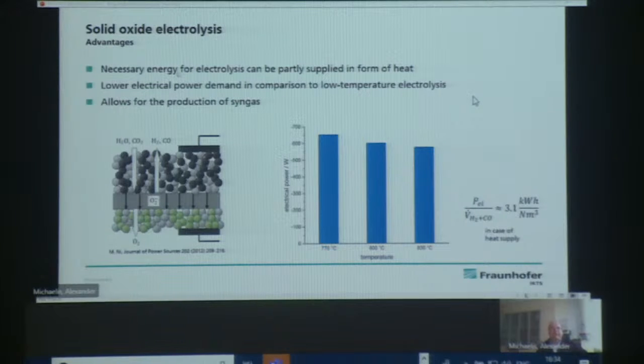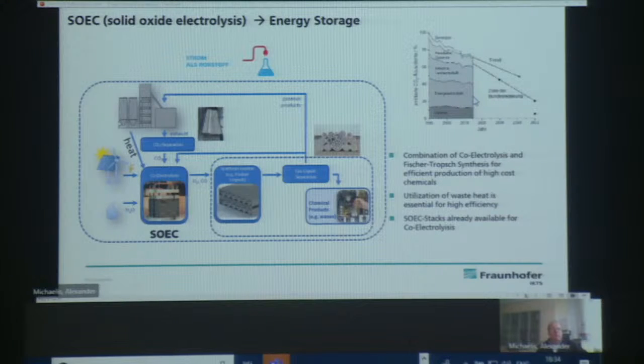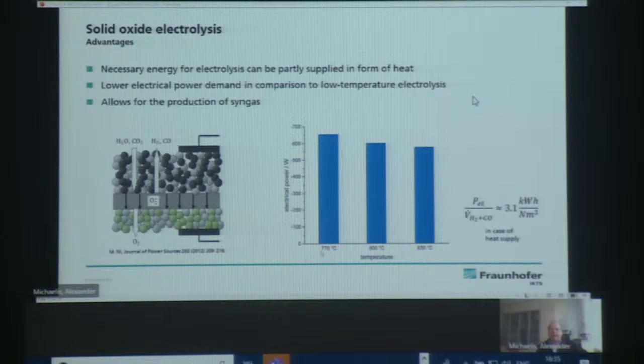This is summarized here again. And one big advantage that I did not mention yet is, or maybe I go back one further, it also uses heat in the energy balance to produce this synthetic gas. So you see here, the higher the temperature of your system, the lower the electrical power demand. And if you go to 830 degrees Celsius for operating, you can use roughly 3 kilowatt hour electrical power to make 1 norm cubic meter of this synthetic gas. This synthetic gas has more energy content than the 3.1 kilowatt hours shown here. That means the heat directly goes into the energy balance. And that means in all cases, when you have waste heat, this is a very nice and very efficient process.